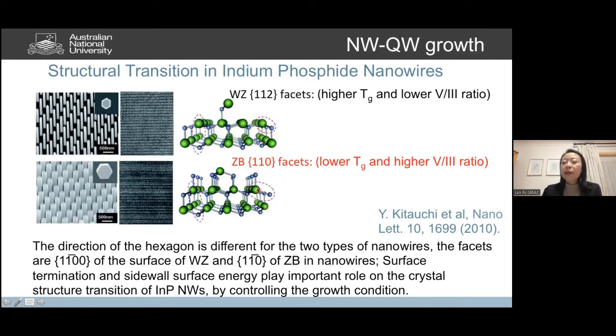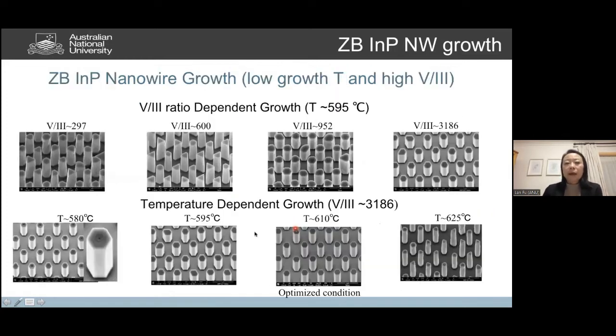We think if we do that, we can actually facilitate indium gallium arsenide growth, which tends to form a zinc blende segment on the top facet. So if we can create that, then we will probably have that rotation of the facet during the growth. So that's basically our motivation. We want to see if we can create another growth window to create zinc blende based indium phosphide nanowires.